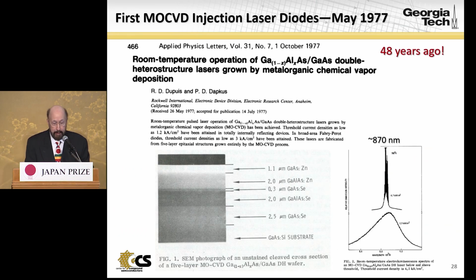Let me now turn to the laser diode work that we began in 1977. While I was working on solar cells, I was also working on laser diodes because my professor, Nick Holonyak, told me laser diodes are important, and I believed him. So we started to work on heterojunction lasers following the liquid phase epitaxy structure that was being manufactured, which consisted of a double heterojunction of N-type aluminum gallium arsenide, P-type aluminum gallium arsenide, and in between a sandwich layer of gallium arsenide. These devices operated pulsed at room temperature, as you can see in this panel, at about 870 nanometers.